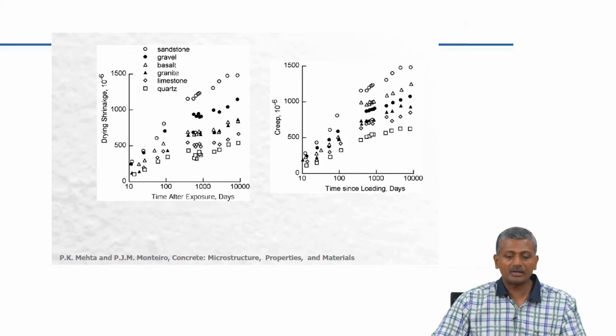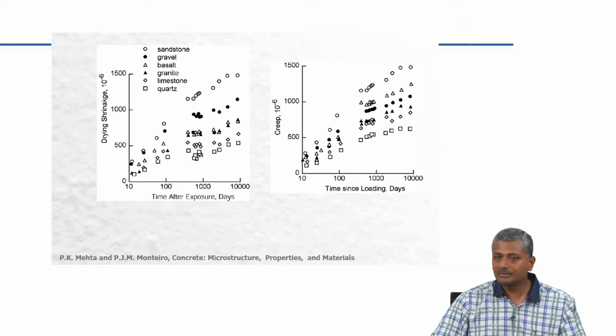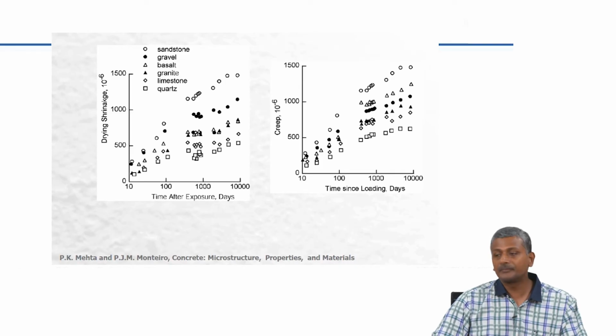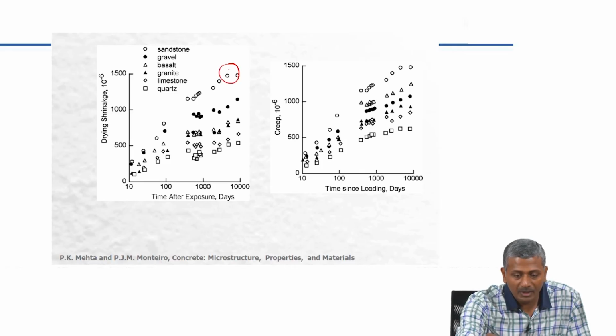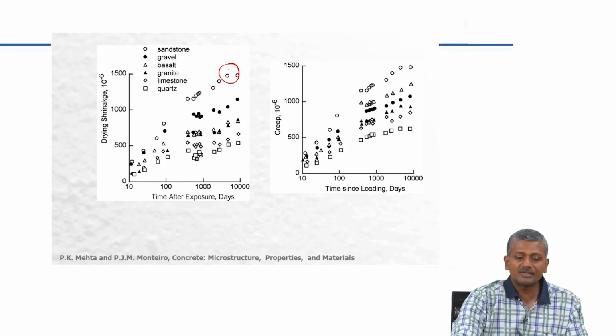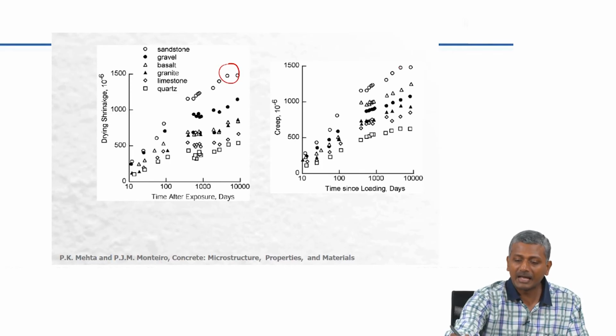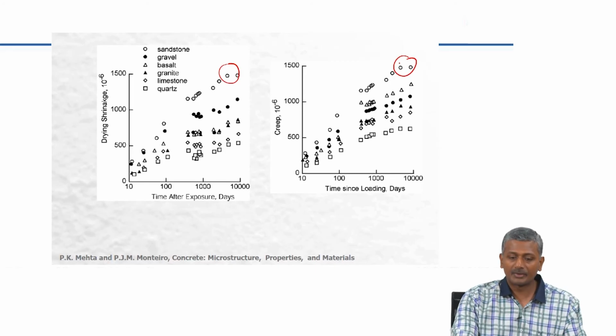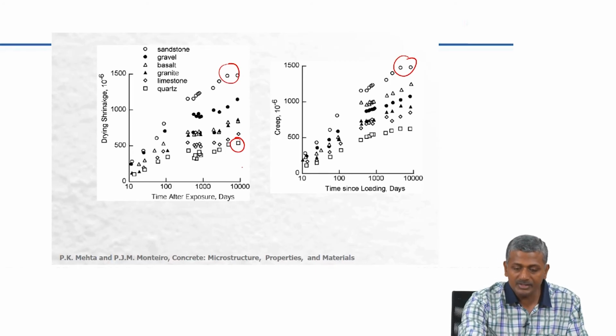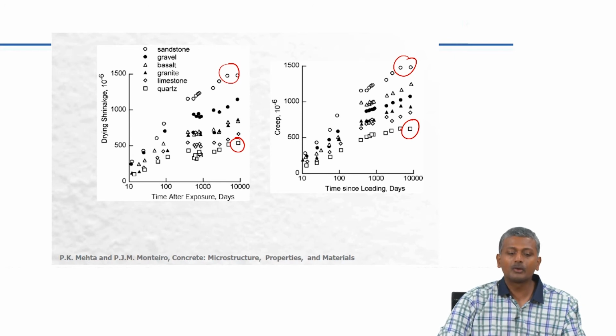So, again shrinkage and creep can be severely influenced with the type of aggregate that is also used in the system. So, you can see here, for example, the extent of shrinkage with sandstone is extremely high, as is the creep with sandstone. Okay. On the other hand, look at quartz aggregate, you get very low shrinkage and creep as compared to the other types of aggregate.